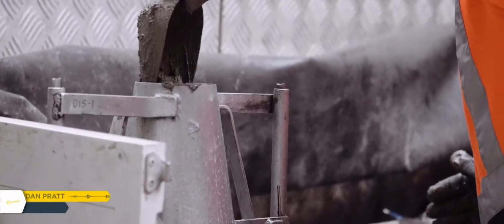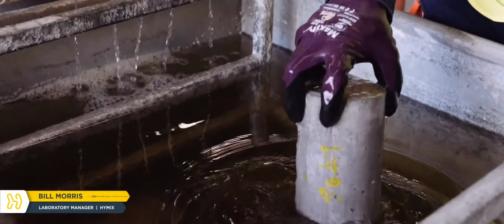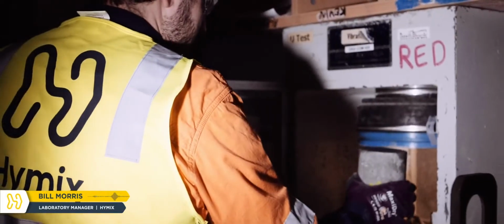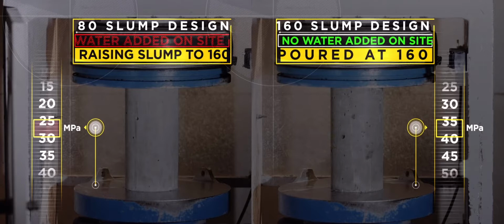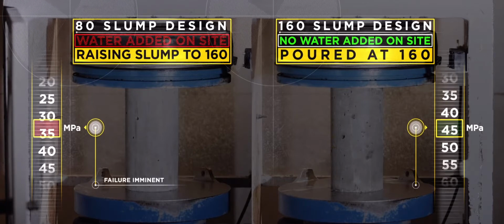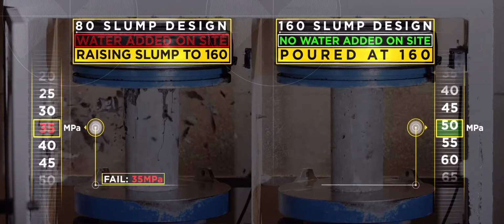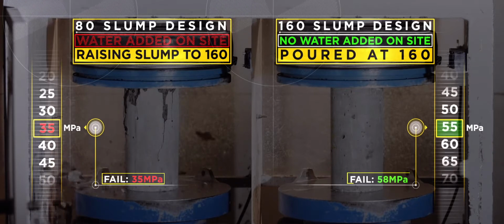When a water-cement ratio is being altered in a mix by adding water on site, generally the information is based on compressive testing of cylinders. Once the samples arrive at the lab, we put them into our temperature controlled tanks. We then do a compressive strength test on the cylinders. If they do fail, one of the biggest reasons is improper water control. That's water being added without it being measured at the plant. And that's where you get the water-cement ratio coming out of line.